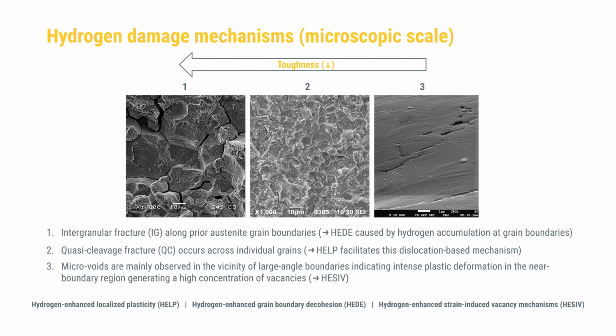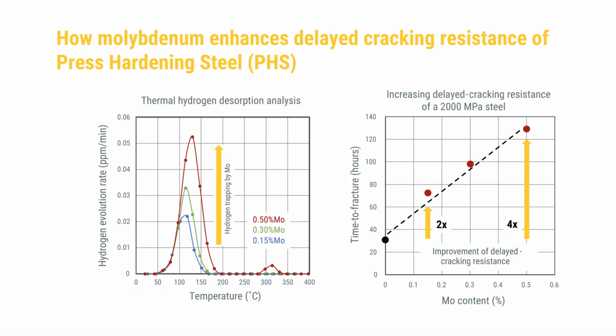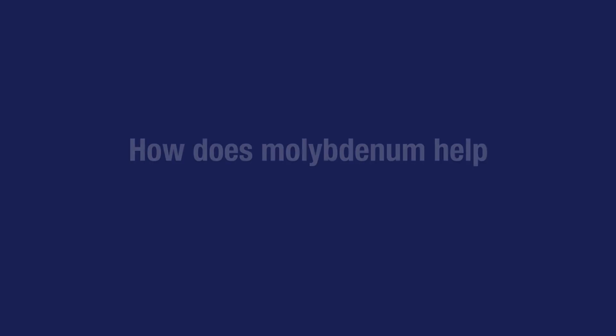So therefore, we actually need to define boundary criteria of how much hydrogen in general is allowable in a steel, what features should be avoided, and in what sense a microstructure should be optimized. But we can say for sure that alloying with molybdenum improves these features, and molybdenum by itself has a very beneficial effect against hydrogen-induced damage.